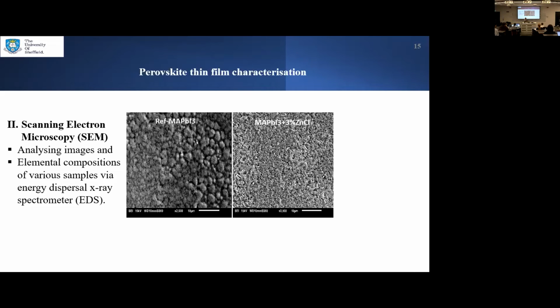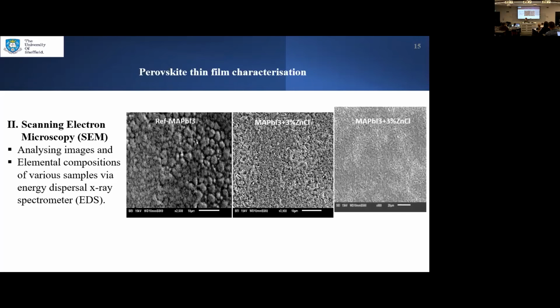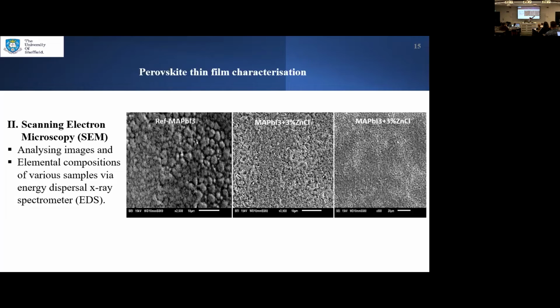And actually, in comparing images using SEM, it is very important to know the magnification of the images being compared. Because once the magnification changes, what you are actually seeing tends to differ, which could be seen from here. In these two results, we changed the magnification of the lens, and we see a slightly different image.